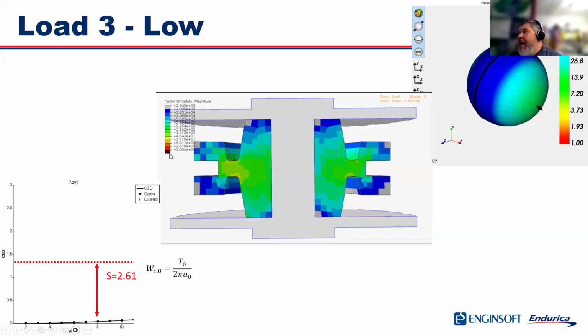And if you see any black in the plot, then that means that the safety factor is less than 1, which means that in those locations you would not expect to have infinite life. Now, for the low load case, the worst case safety factor in this simulation was about 2.6. So this grommet would be qualified for infinite service under the low load case.